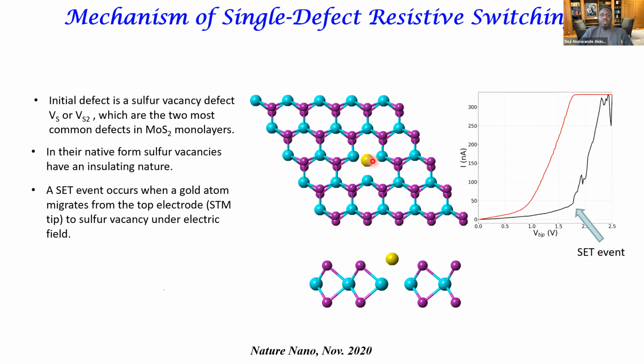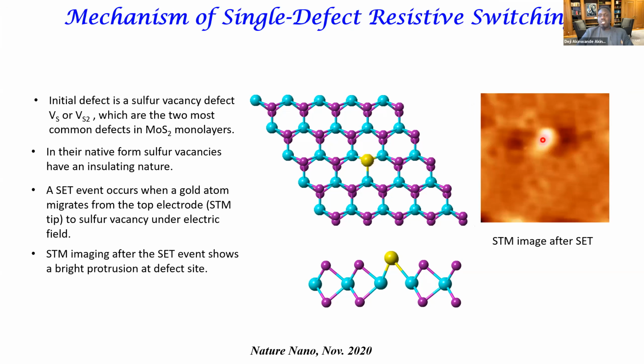The hypothesis then is that the gold atom is going to be adsorbed and bond to that vacancy. To prove that, he now goes and does imaging exactly at the same spot, and then we see a bump in the place where the defect, the vacancy, was present. We've done analysis, the geometry of the bump correlated with DFT calculations. We conclude that this is a gold atom sitting on this vacancy.